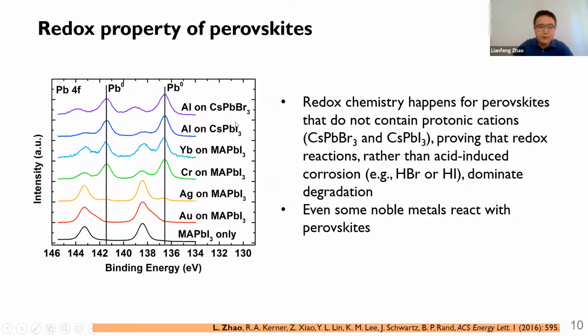So we further tested the redox chemistry on different perovskite compositions and on different electrodes. What we found is that the redox chemistry also happens for perovskite compositions that do not contain protonic cations, such as the case for cesium lead bromide and cesium lead iodide. This observation proves that it is not an acid-induced reaction, but rather redox reactions that induce the degradation. And furthermore, we found that these reactions also happen for more or less stable electrodes such as silver and gold.